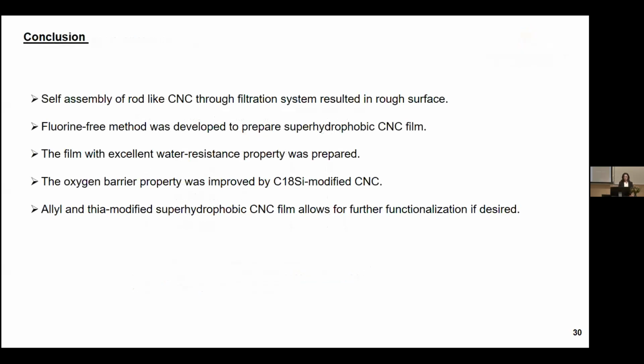The conclusion of this paper is that the self-assembly of rod-like CNC through a filtration system resulted in a rough surface. A fluorine-free method was developed to prepare superhydrophobic CNC film. The film with excellent water-resistant property was prepared. The oxygen barrier property was also improved by CNC that was modified with octadecyltrimethoxysilane. Also, the allyl and thiol modified superhydrophobic CNC film allows for further functionalizing if desired.